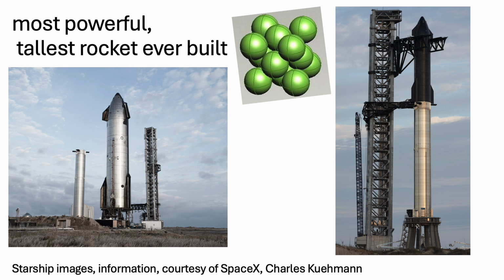Both the spaceship and the booster are made of stainless steel, which is in its austenitic condition, but is cold rolled so that the strength is in excess of 2 gigapascals. And the specific strength compares or even beats that of aluminium lithium alloys, which are normally used for rockets of a smaller size. And the steel is only 3 millimeters in thickness, and yet the rocket doesn't collapse under its own weight when it is not pressurized.